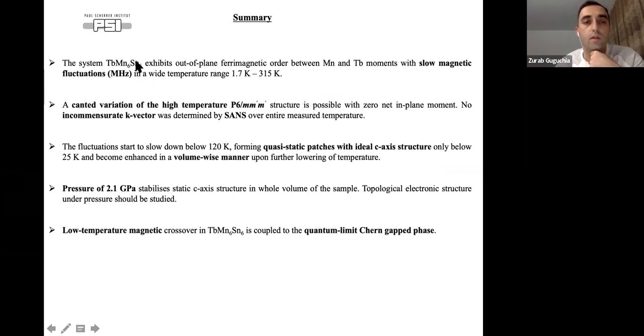Okay, so to conclude this part, we did also a lot of neutron diffraction on the sample. So we see that we have out-of-plane ferrimagnetic ordering between manganese and terbium with slow magnetic fluctuations. However, we see the fluctuations slow down below 120 Kelvin, forming quasi-static patches with ideal C-axis structure only below 25 Kelvin. And then it enhances in a volume-wise manner. So we saw that a pressure of 2.1 GPa stabilizes the C-axis structure in the whole volume of the sample, and it would be nice to measure the topological electron structure under pressure, which we did not do so far. And so we see the low temperature magnetic crossover is coupled to this interesting low temperature topological phase of this material. And so we could exclude any incommensurate K-vector from the small angle neutron scattering measurements.